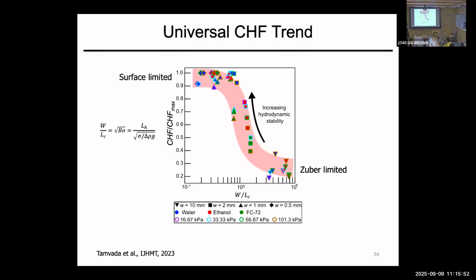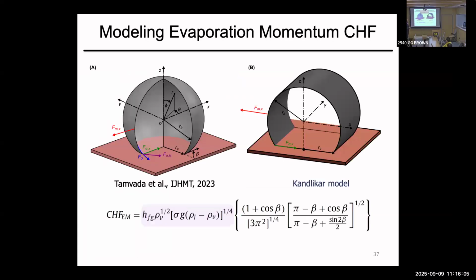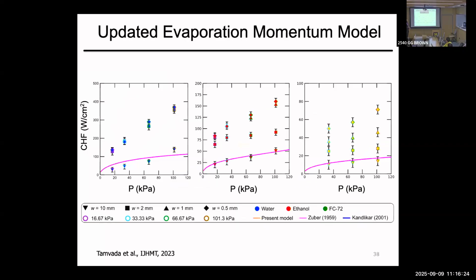So we said this must be a surface limit, what people discussed in the 90s, rather than what people thought about in the 1930s, 40s, and 50s. So we went back to Kandlikar and looked at how his model predicts the same number that everybody else did, just like Zuber. We realized that he made an assumption that the bubble is essentially a cylinder. So we redeveloped the model for a sphere. If you do that and use experimental numbers for contact angles, you get a nice prediction for water, ethanol, and FC72.